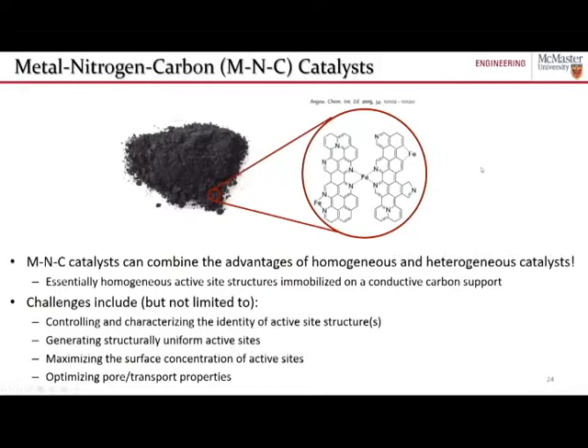One is controlling and characterizing the identity of the active site structures. Particularly, as I mentioned, these materials are prepared by blending a bunch of precursors together and heat treating them at 900 degrees in nitrogen. So you can imagine at those hot temperatures, it's really hard to control what structures are formed, whereby we want to maximize the formation of the most active catalytic sites. But being able to direct the synthesis towards these target active sites also requires us to understand what those active sites look like and what their properties are.